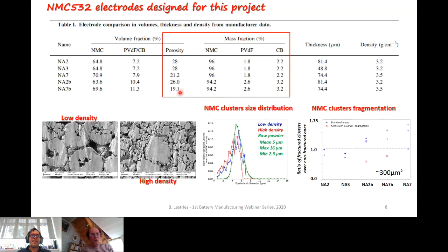Okay, so you can see here some SEM pictures of the electrode cross sections, and you have here the NMC cluster size distribution. In the raw powder, the NMC cluster has a mean particle cluster size of 5 micrometers. You see that some of them are hollow, and what can be observed in the high density electrodes is that a significant part of the NMC clusters have been fragmented into smaller particles, in fact primary particles, due to fracture at the grain boundaries.